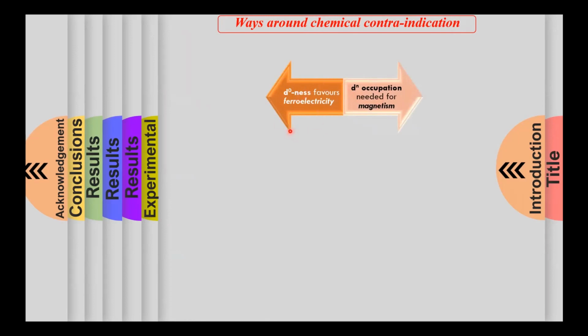Most of the ferroelectric materials are transition metal oxides in which ferroelectricity is driven by the displacive mechanism and is favored by the empty d shells on the transition metal ion. In contrast, magnetism occurs when materials have partially filled d orbitals. So we see that d0-ness, that is empty d shell, favors ferroelectricity, while the partially filled d shells favor magnetism. So this is a contraindication because it is very difficult to fulfill both the conditions simultaneously.